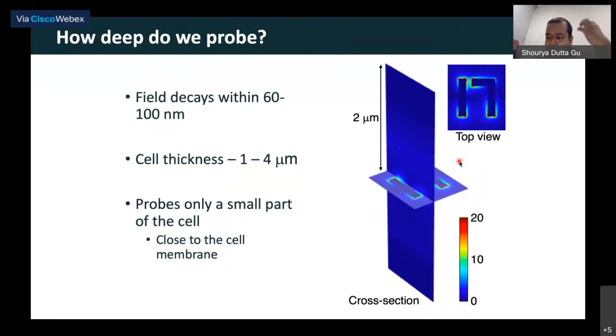Now, since we are interested in looking at how cells are responding to these structures, we also need to look at how deep we are actually probing into the sample, right? What is the depth that we are actually getting the signal from? So this is a calculation where we are plotting the field in the XY plane, which is this horizontal cut, and the Z axis, which is in the vertical direction. Now, if you notice, this is around 2 microns in height. So if you notice this region, which is shown in red and green, it is very, very small as compared to this. And this region is around 60 to 100 nanometers from the surface of the structure.